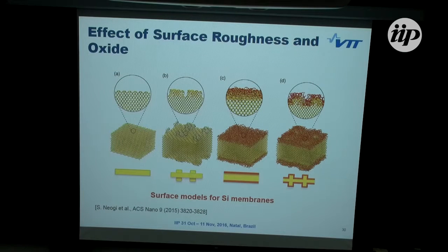And this was already explained by Davide. So there are different samples or different kinds of models. The reason these look like this is that in real samples, when there's a native oxide on top of silicon, it looks something like this, roughly. The surface is a little bit undulating, and the thickness of the oxide, which is not included here, also varies a little bit. So this is something that is close to real samples.